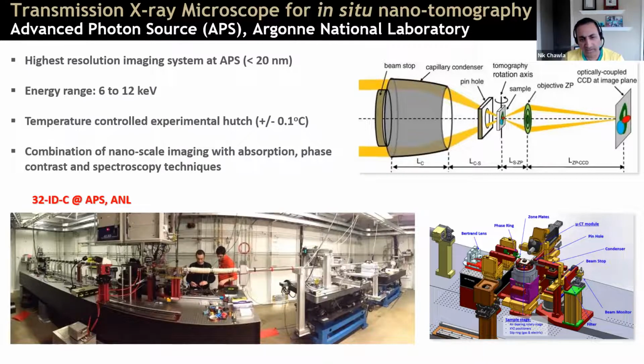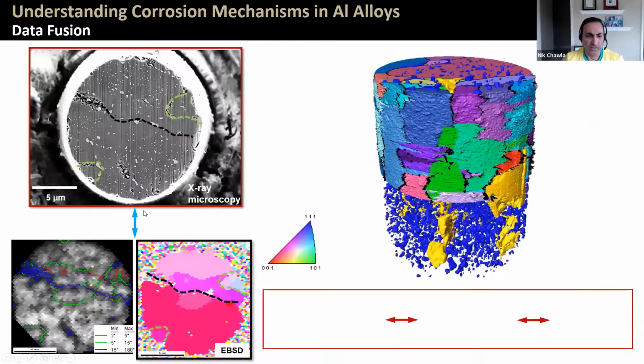This particular data set was acquired at the transmission X-ray microscope beamline. It's a TXM, transmission X-ray microscopy, much lower energies, but we can get to resolutions down to about 20 nanometers or less. And so here is an example of intergranular corrosion in an aluminum alloy.